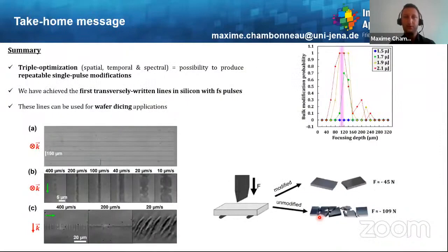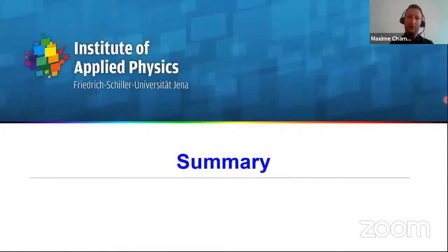So here is the take-home message for this last part. By using a triple optimization in the spatial, temporal, and spectral domain, we were able to produce some repeatable single-pulse modifications. We have also achieved the very first transversely written lines inside silicon with femtosecond laser pulses, and those lines can be used for wafer dicing applications. So, to summarize,